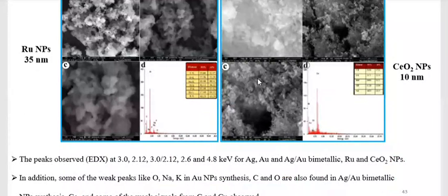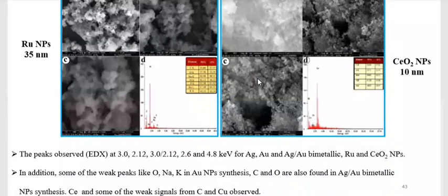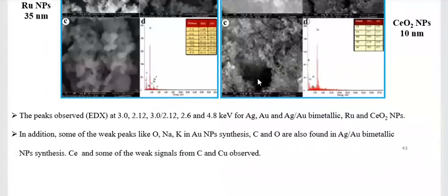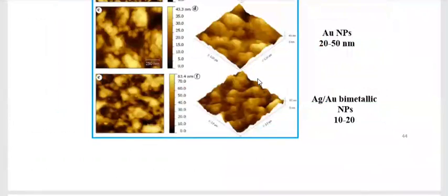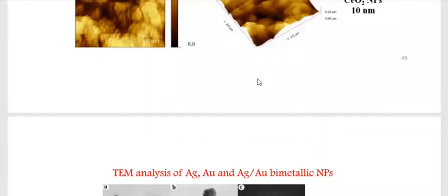AFM analysis gives the surface topology, without the effect of an electron beam. It can be in conducting mode or non-conducting mode; generally it is taken in the non-conducting mode. It shows 20 to 50 nanometers for silver and gold, and 10 to 20 nanometers for bimetallic. The ruthenium particles show 20 and cerium oxide 10 nanometers.